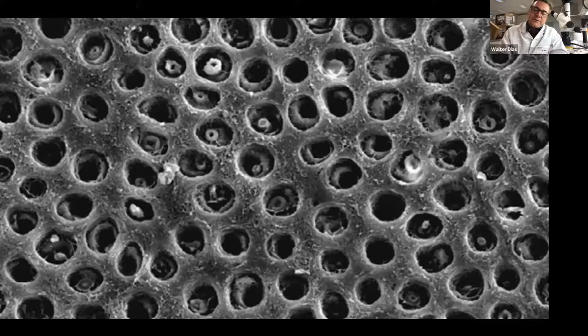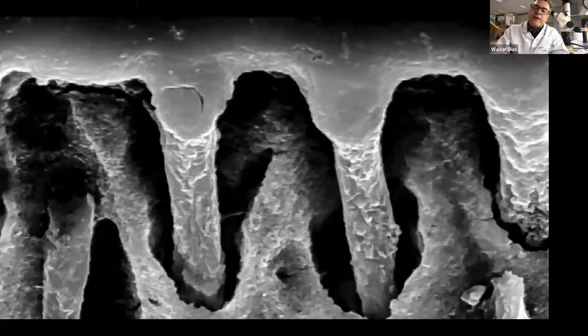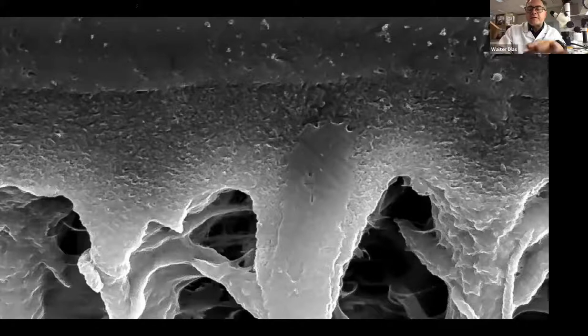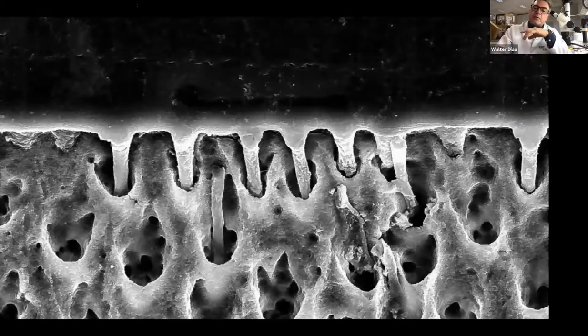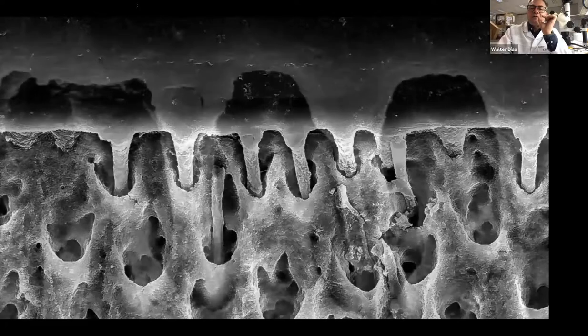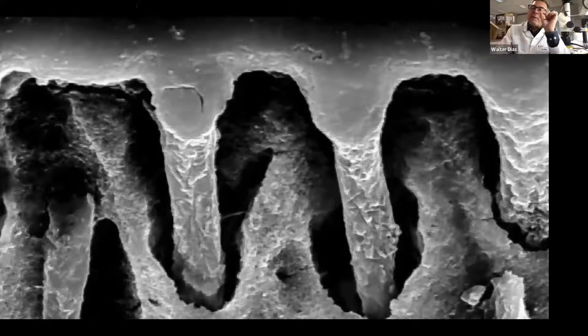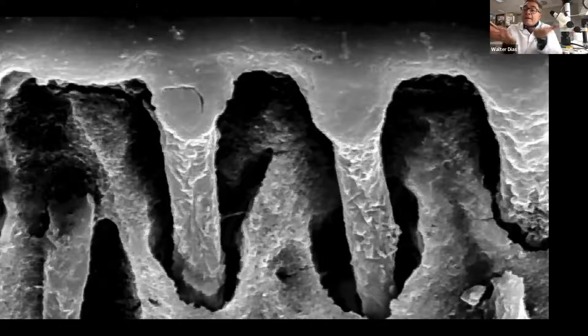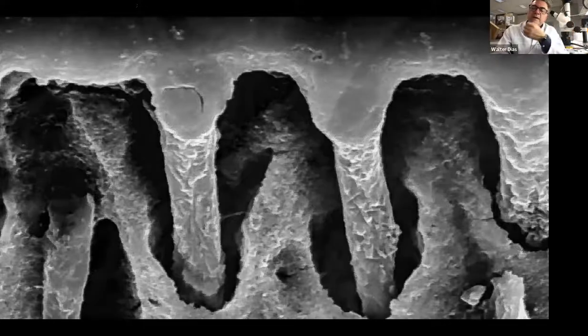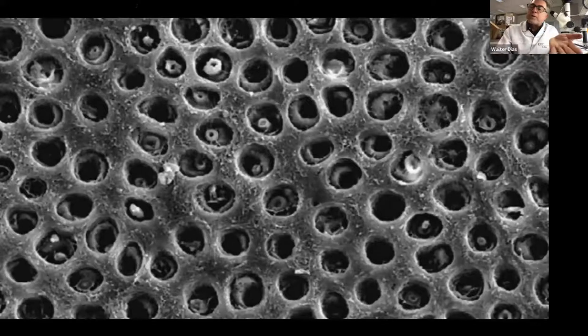That's why today we're recommending that we use a self-etching adhesive. Let me show you here. This is Prime&Bond Active in total etch mode. Let me show you how it looks in self-etch mode. You have a much more conservative etching inside the tubule. You have a much thinner hybrid layer, which is easier to achieve because it's easier to saturate with adhesive. And the bond strength is equivalent in an optimal scenario, but this bond strength is much easier and more predictable to obtain. So that's why we're trying to always go for self-etching on sound dentin.